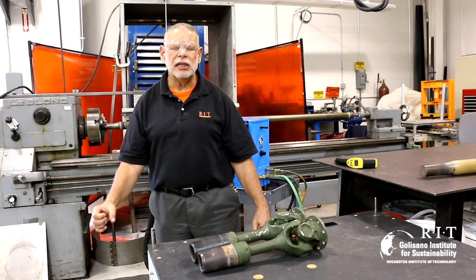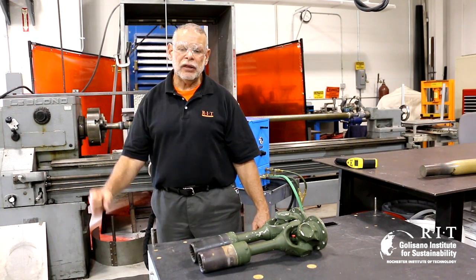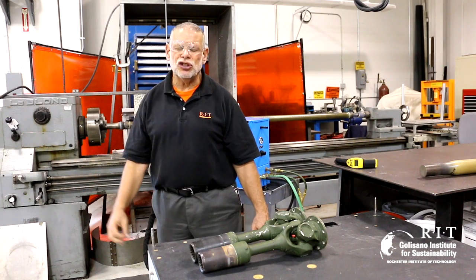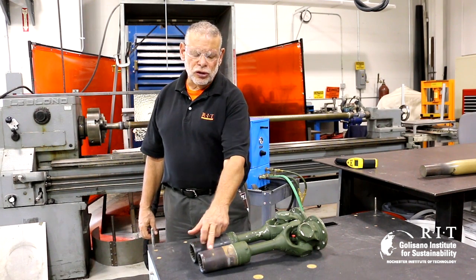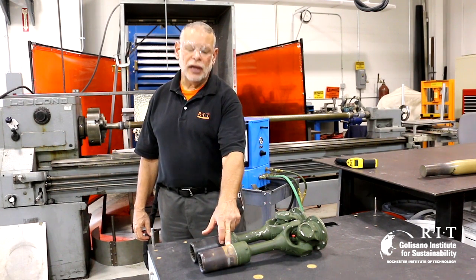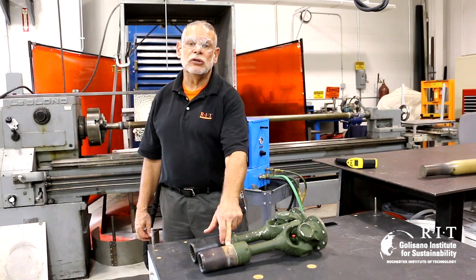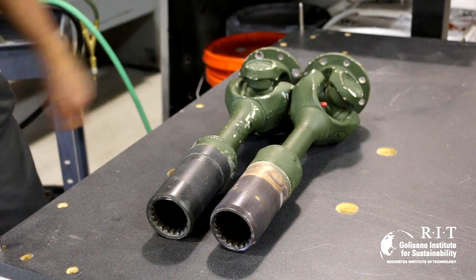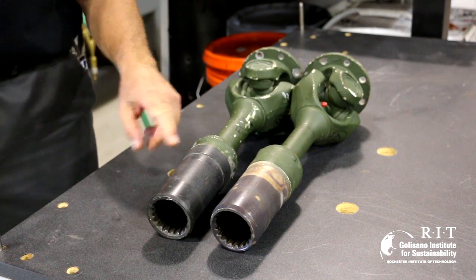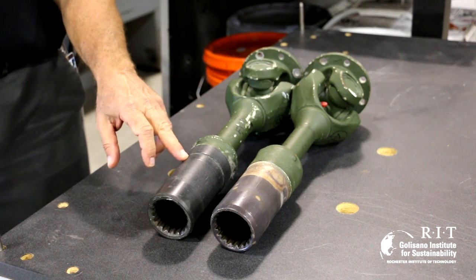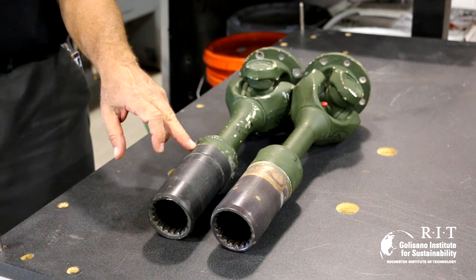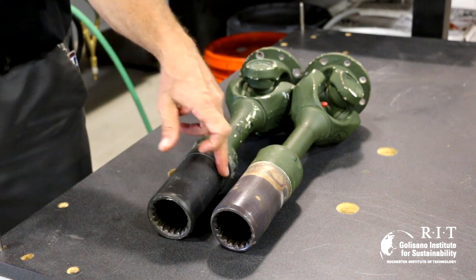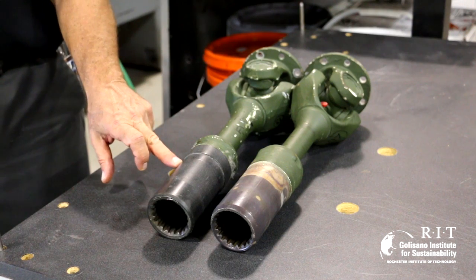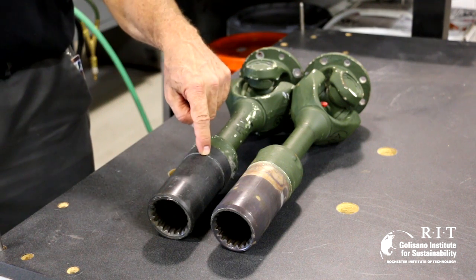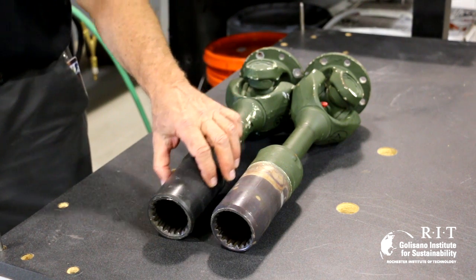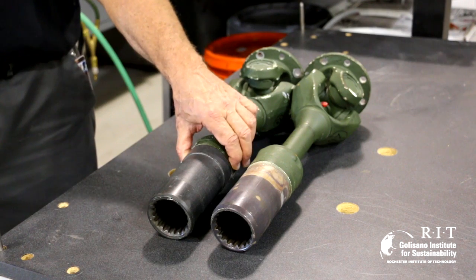So we had to use a remanufacturing process that was different than the original process. The original process, they dipped the material in a bath, pulled out the coating, and then machined it to shape. We were going to just coat one side of it, and we had to keep the temperature below 200 degrees F. This is the remanufactured component. You can see it's different from the original one in that we brought the coating up over the step. This prevented the debonding of the coating from the step and prevented water from getting underneath it, actually, so it made the part better than new.